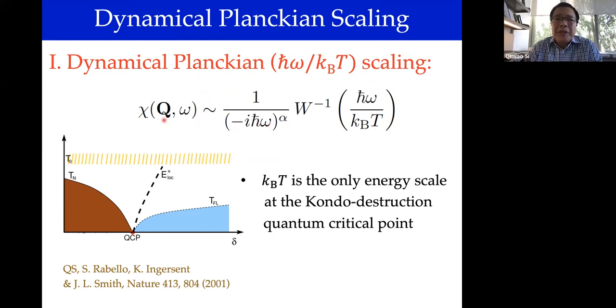I already alluded to that the Bose-Fermi Kondo model has ħω over k_BT scaling. In the lattice model, this would show up at the quantum critical point, and at the antiferromagnetic wave vector as the dynamical spin susceptibility as a function of frequency and temperature would have a form like this, where it has a singular frequency and temperature dependencies, and the collapse onto ħω over k_BT scaling.